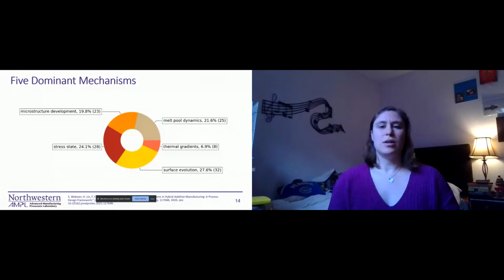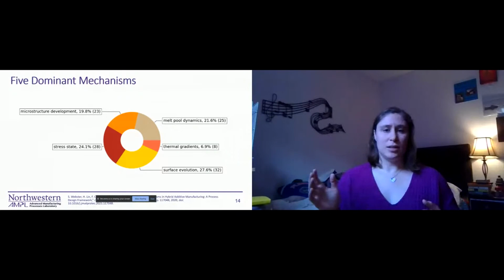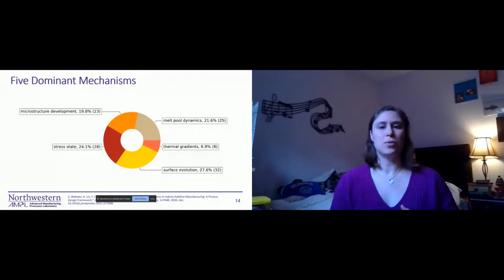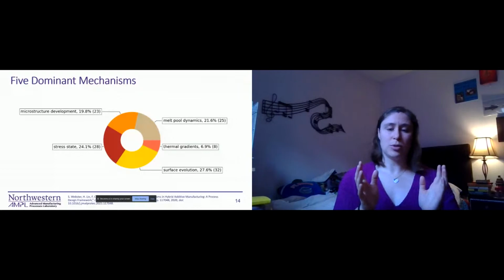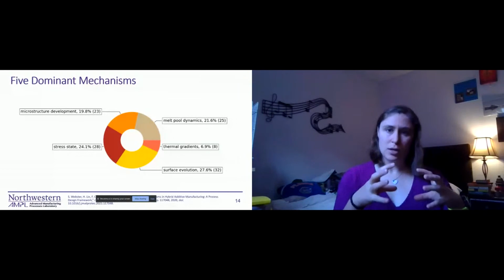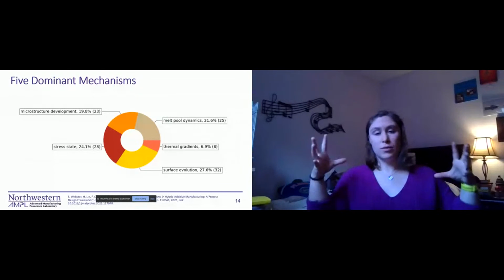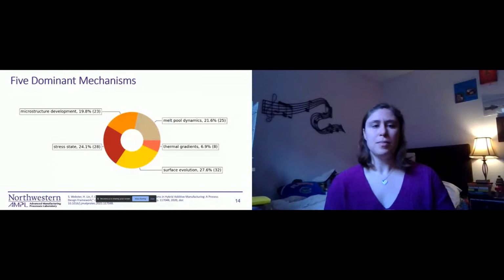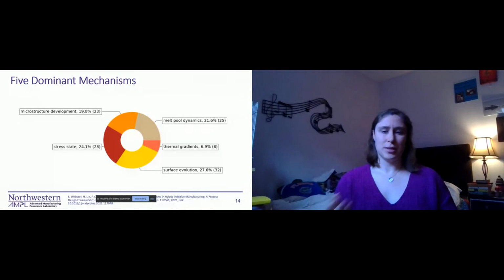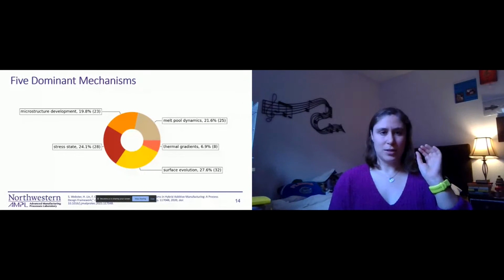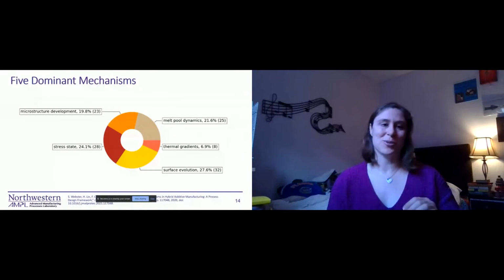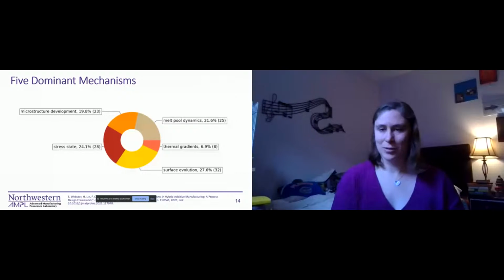Melt pool dynamics are mainly affected in deposition rate, or the melt pool flow pattern, and velocities in the melt pool. The thermal gradients actually either looked at or controlled temperature gradients within the melt pool, so very local temperature gradient, or even looking at the global thermal gradient. Microstructure development is obviously influenced by both melt pool dynamics and thermal gradients, but there are specific energy sources that were used for only looking at the microstructure.